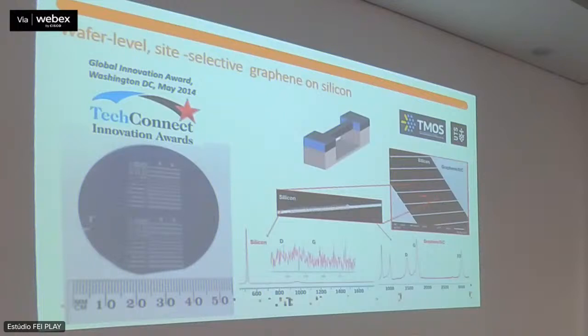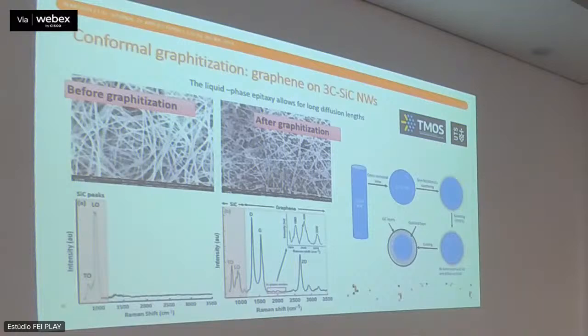And by looking at the Raman, you can see that wherever you see this black silicon, there is no graphene. You see that here, silicon. And the whitish part here is actually graphene with silicon carbide. Silicon carbide peaks are here, and this is the graphene. So it really works selectively at the wafer level, which is really something we want to have. But not only that, this can also be scaled down to very, very small structures. And this was just a case study to prove that.